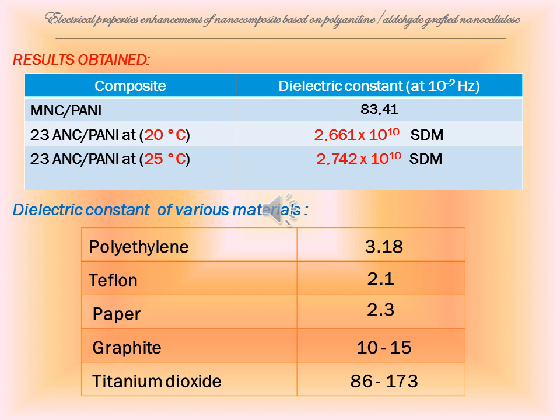Results obtained. The dielectric constant of the MNC PANI composite equals 83.41 at 10 to the power of -2 Hertz, of course, while the dielectric constant of 23 ANC PANI equals 2.661 times 10 to the power of 10 at 20 degrees Celsius, and equals 2.742 times 10 to the power of 10 at 25 degrees Celsius, of course at 10 to the power of -2 Hertz.